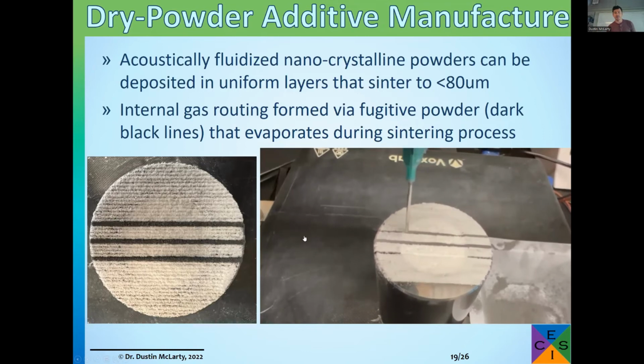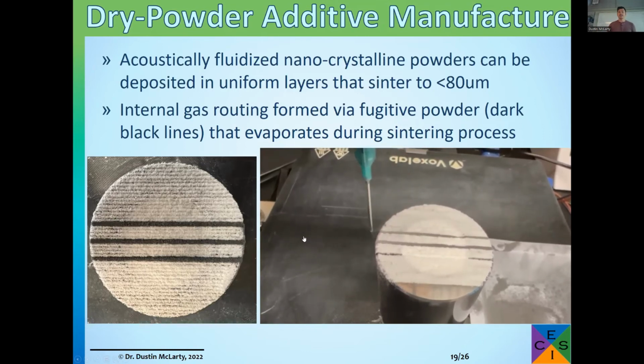And what this is showing, that's depositing a layer of fugitive material. The white powder there is YSZ, which is your typical electrolyte in a high temperature fuel cell. And we can deposit interspersed into that fugitive material that will evaporate out of the assembly during the firing process. So we can leave behind these microchannels for gas routing, and we can do all different layers. So we print a layer, press it, print a layer, press it, and do additive manufacturing in that sense.